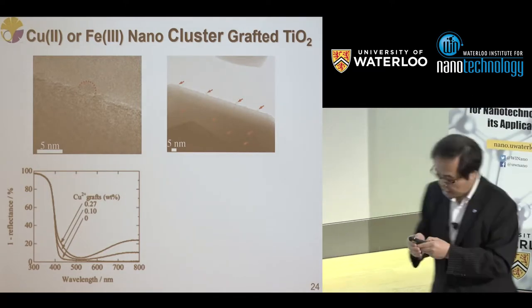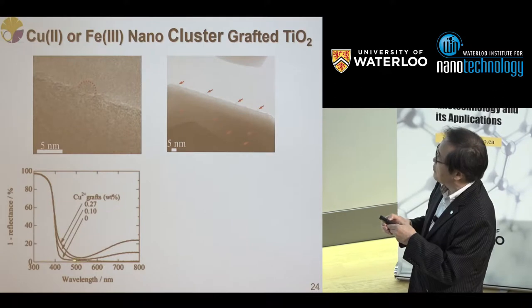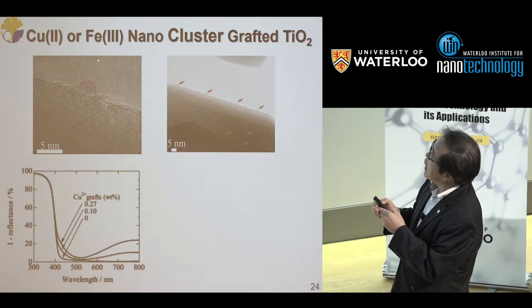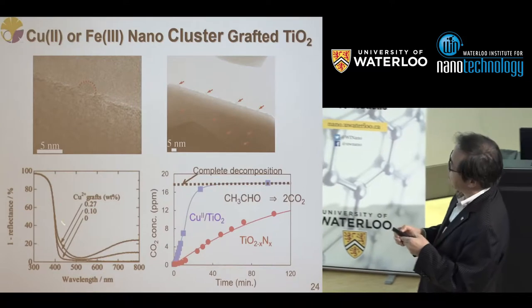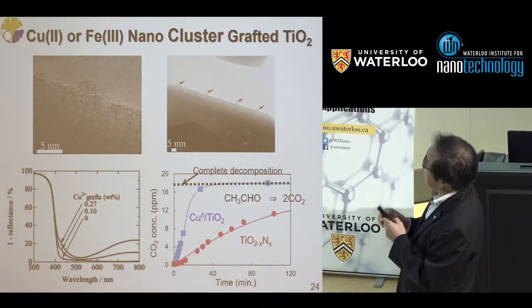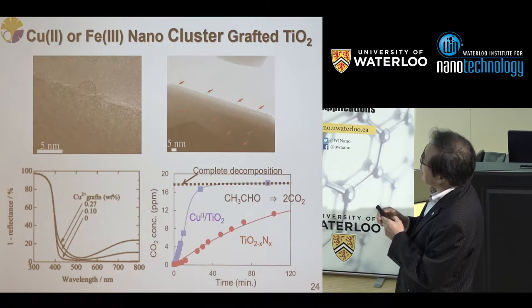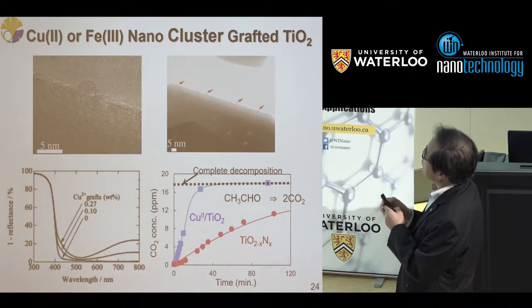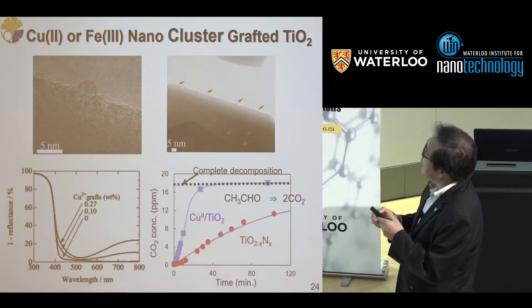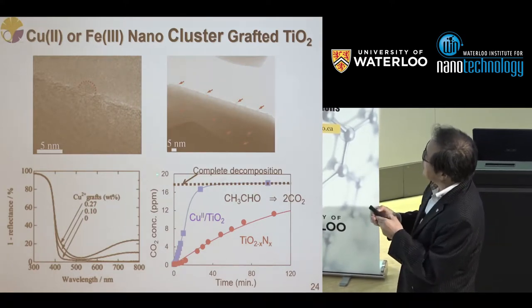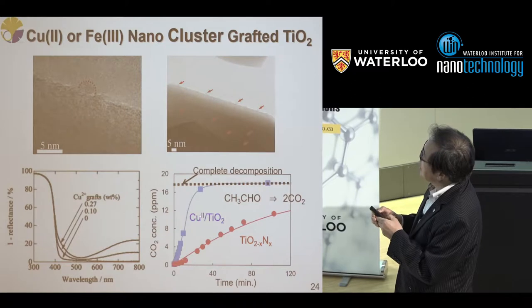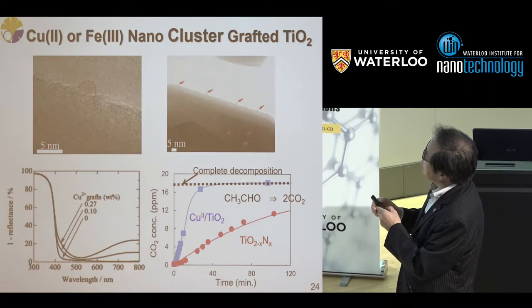Absorption, this one is a d-d transition, so it doesn't work. But this one is a new band that appears by introducing divalent copper or trivalent iron nanocluster on titanium dioxide. And when we illuminate this band, okay, this is the decomposition of acetaldehyde. When acetaldehyde is completely decomposed, 2 CO2 molecules are produced. And this is the complete decomposition, the concentration. Okay, in the case of divalent copper nanocluster modified, grafted titanium dioxide, it comes to complete decomposition soon.